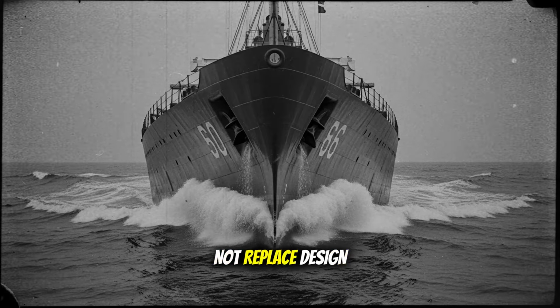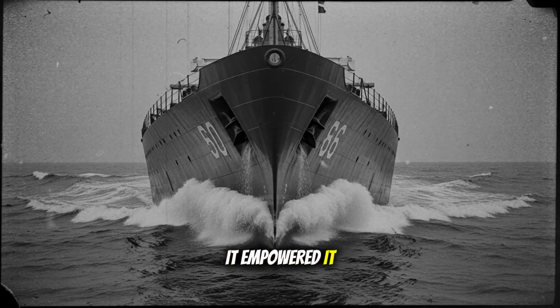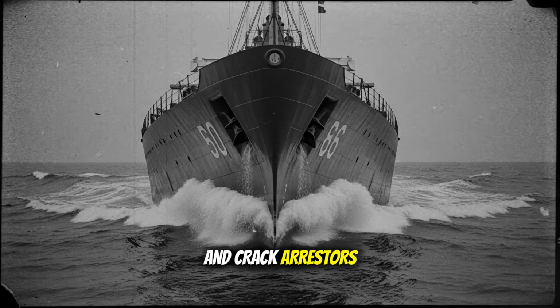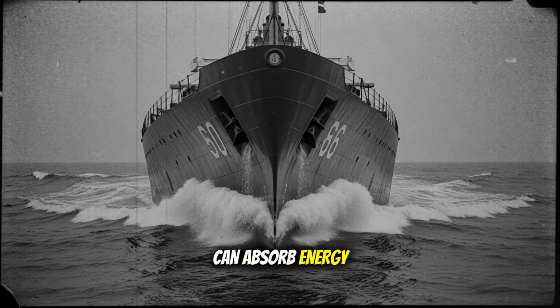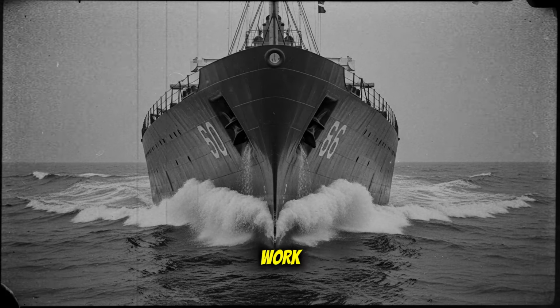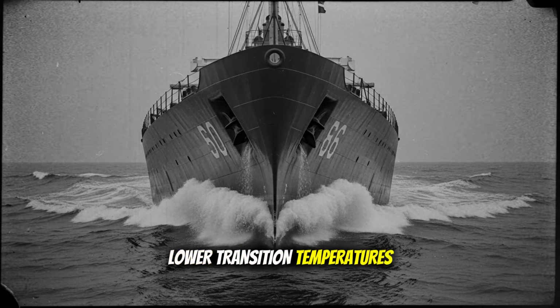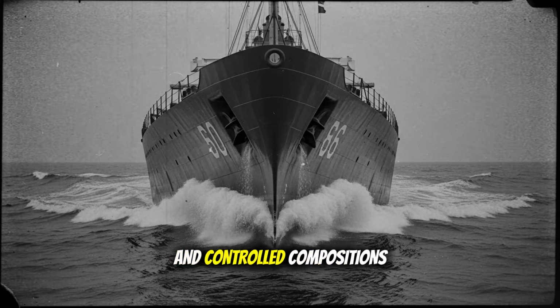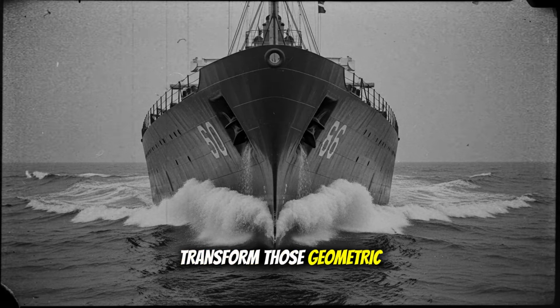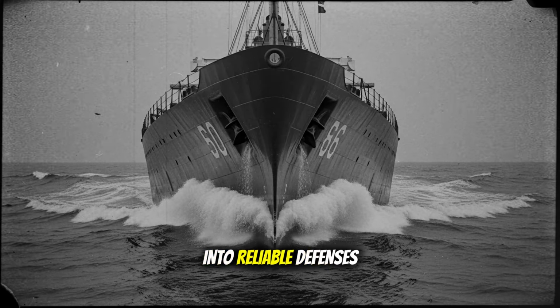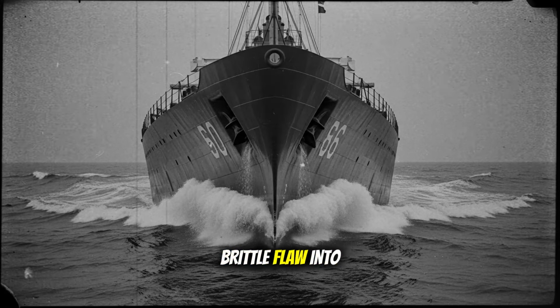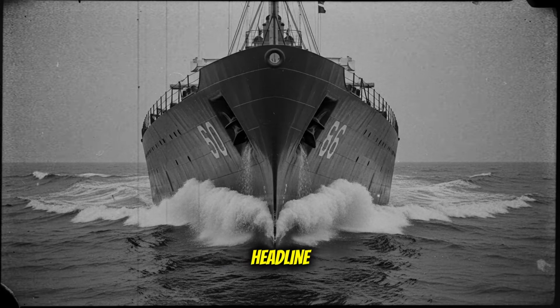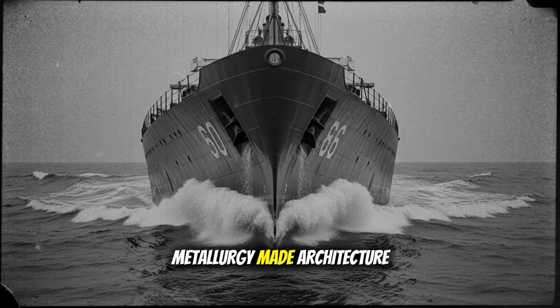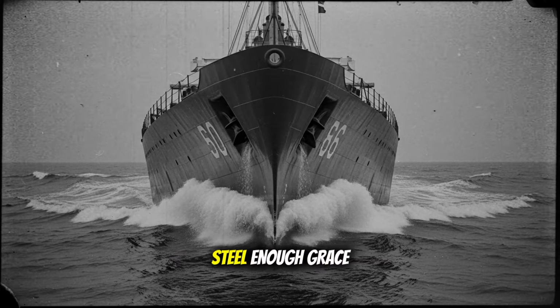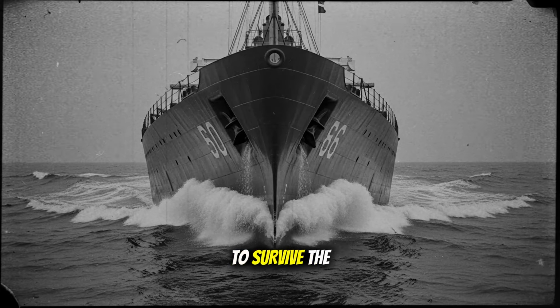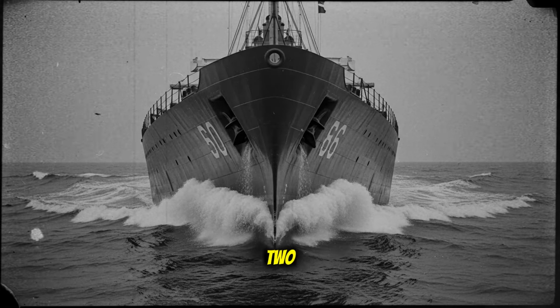Material change did not replace design change, it empowered it, because rounded corners and crack arresters only matter if the plate can absorb energy at the temperature where they are called upon to work. Lower transition temperatures, cleaner weld zones, and controlled compositions transformed those geometric fixes from good intentions into reliable defenses, turning a single brittle flaw into a contained repair instead of a headline. That is how metallurgy made architecture honest, by giving the steel enough grace at the notch in winter to survive the moment that once split ships in two.